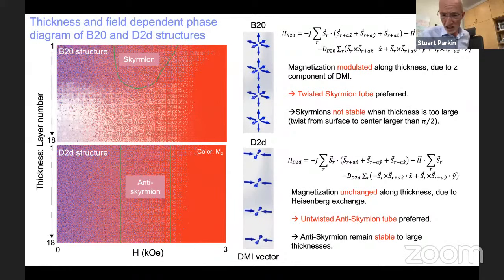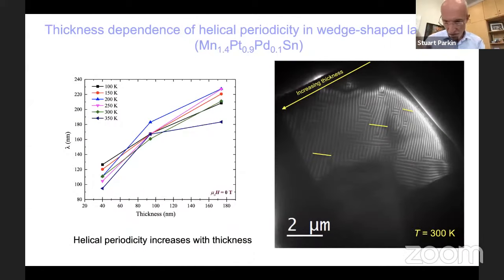Whereas in these D2d systems, there is no component of this vector, the Dzyaloshinskii-Moriya vector, perpendicular or along the tetragonal axis. And in this case, you, in principle, should find tubes, columnar regions, which are stable as independent of thickness. But an important point is that we discovered that actually both the period of these helices that I mentioned, plus the size of these antiskyrmions, evolves with thickness considerably.